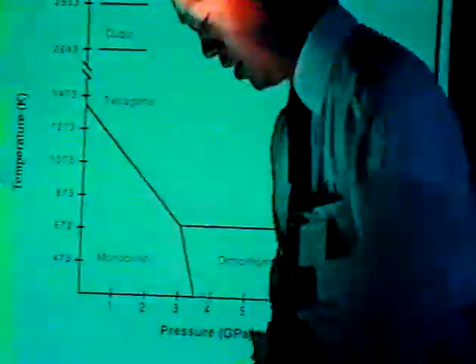which I will refer to as an intermediate gel time, did we manage to synthesize the zirconia aerogel that has a narrow pore distribution containing mostly mesopores, and this particular zirconia aerogel has a surface area of about 120 to 130 meters squared per gram after calcination at 500 degrees Celsius. So what I have shown you so far is the effect of gel time on 2 properties, namely the BET surface area and the corresponding pore volume.